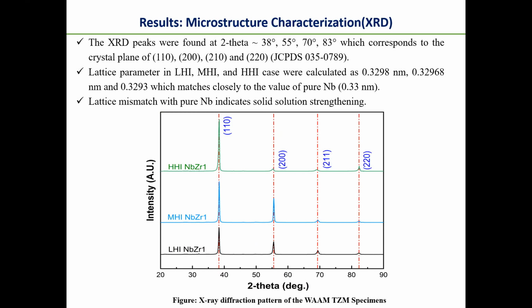And after that, we did the XRD analysis to find the phase constituents, if there is any other minor phase apart from the niobium phase. We found that the major peaks of the XRD are around 38, 55, 70, and 83. These peaks correspond to 110, 200, 211, and 220, all BCC phase according to JCPDS 035-0789. The calculated lattice parameters were 0.3289, 0.329, and 0.3293 for the low, medium, and high heat input cases, which closely matches pure niobium. The slight change in the lattice parameter also indicates solid solution strengthening, which is the major strengthening mechanism in niobium zirconium 1.